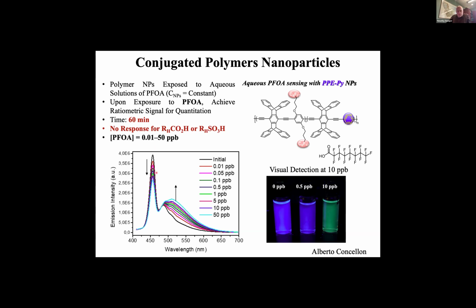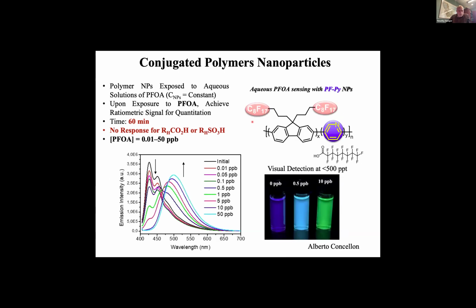But an advantage of this ratiometric detection is we can get quantitation out of it too. So we can use these two signals, one going down, one going up, as essentially an internal standard to give us quantitation. Now, we have a number of different polymers we've made that do this. This one gives a very clear color change, at least to your eye in this figure. At 500 parts per trillion, you can actually detect this visually just looking at it in this solution. So we have these nanoparticles in solution. They're being activated by this, and we see detection.